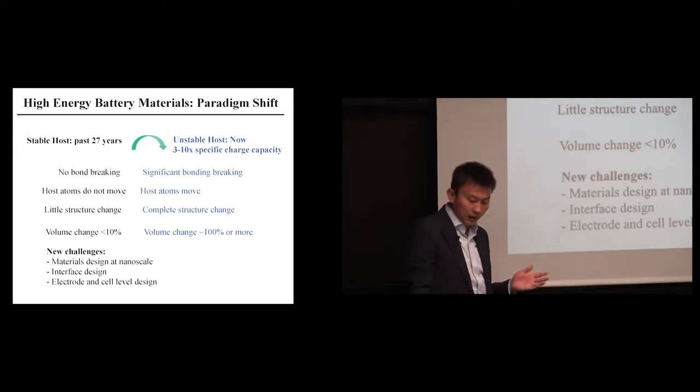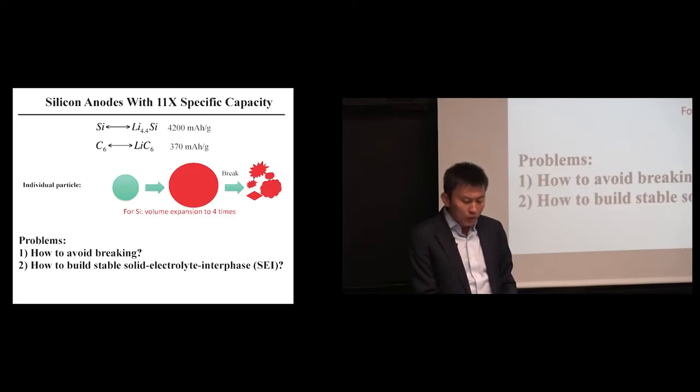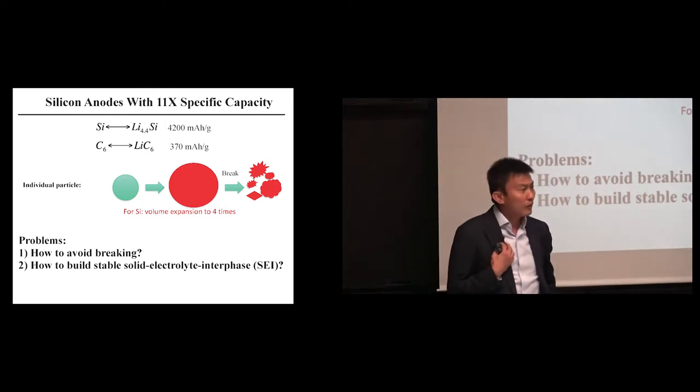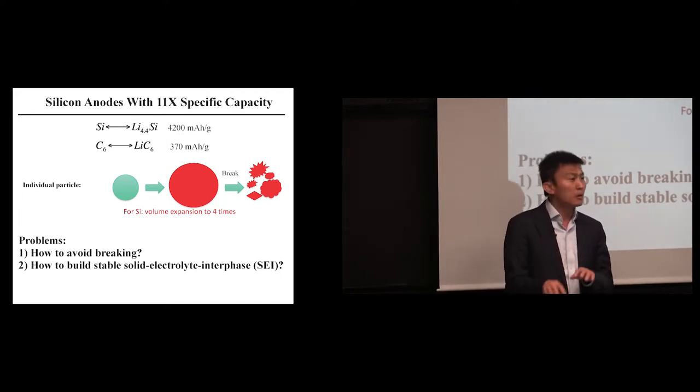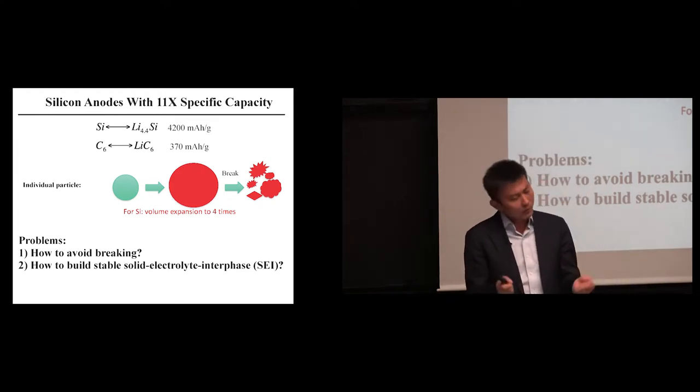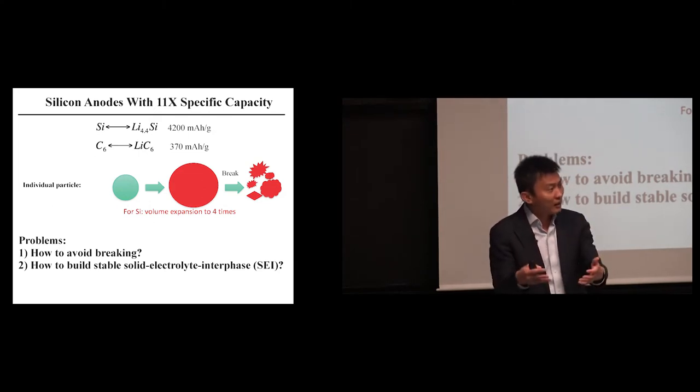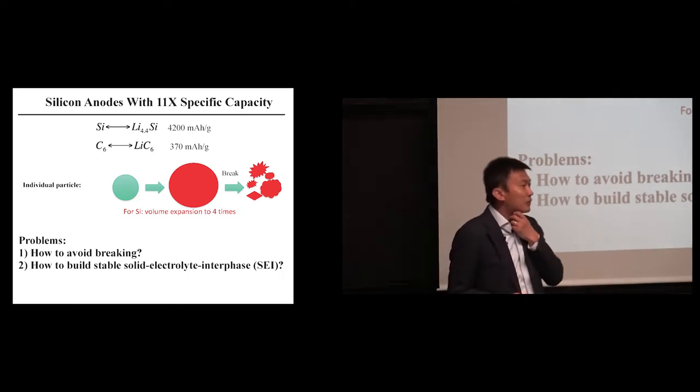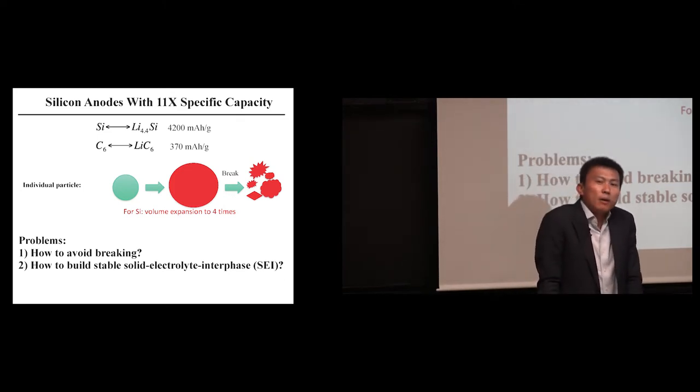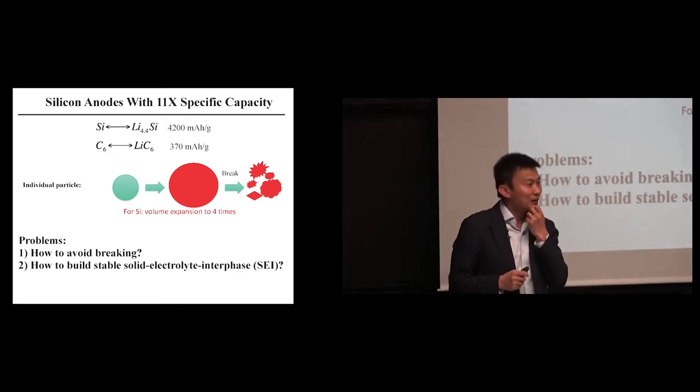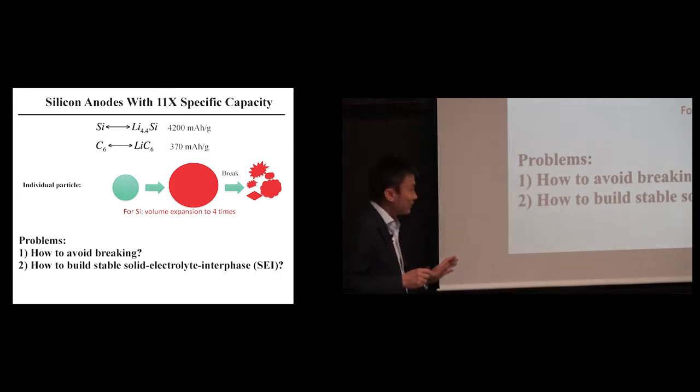Traditional host materials, we know it hosts lithium ion coming in, whether it's graphite or lithium cobalt oxide. These host materials are stable. There's really no chemical bond breaking. Through intercalation, in and out, very nicely, very gentle. New host materials store so many more lithium ions. You're dumping in so many lithium ions, so many electrons. You're chopping down the chemical bond inside these host materials. The host atoms will need to move because of significant bonding change, large volume expansion, complete structure change. You're talking about 100% or more volume change compared to traditional materials. These are the challenges we have to face. How do you design the materials to overcome those completely different paradigms of change at the nanoscale, the interface, the whole electrode, and the cell scale?